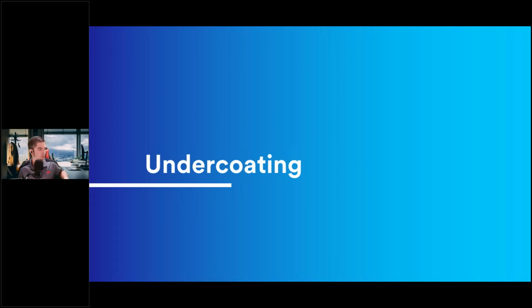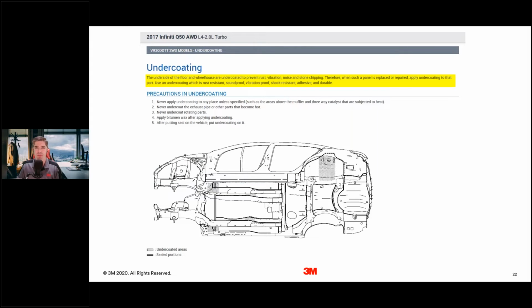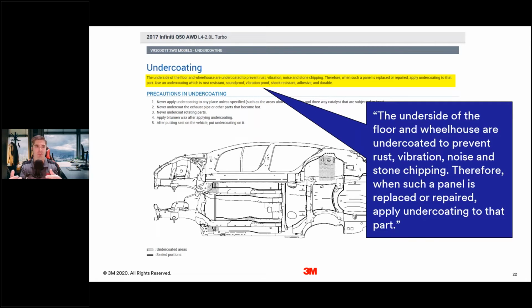So getting into undercoating and understanding, again, as one of those three legs, the importance of it as part of the repair process and what the OEMs are saying. Many of these vehicles may not come with undercoating in these locations from the factory because the coatings that they put on from the factory are able to withstand much harsher conditions than some of the stuff we're using in the aftermarket. They go through extremely high temperature baths that are baked at over 400 degrees for 30 minutes or more. And they've identified that in some cases it's to help absorb vibration and stone chipping, where from the factory they might have other coatings that do this. We need to make sure in the aftermarket that we're applying these.